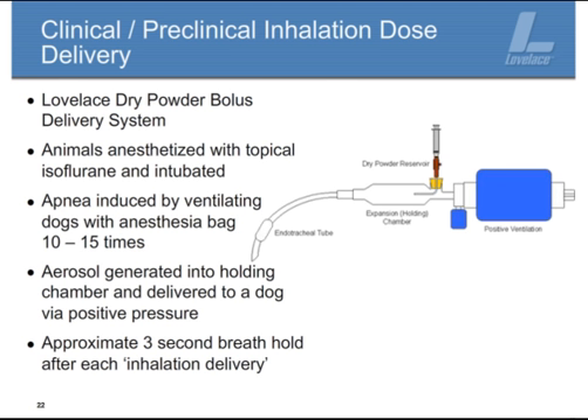In doing this, we aerosolize the material from the dry powder reservoir into the holding chamber. Immediately after we deliver that aerosol into the holding chamber, we do a forced maneuver to the dog that is not breathing on its own and deliver that aerosol to their lungs, followed by about a 3-second breath hold. While we can't get a perfect clinical maneuver with this, there are some subtle differences. This maneuver allows us the best opportunity to take well-engineered materials and do a clinical type maneuver to these animals.